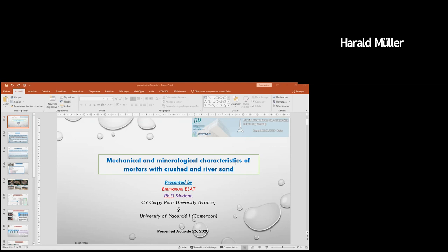And on the other hand, if you look at your slides, on the left-hand side you showed the differences in compressive strength, which has been a little bit questioned by Arnaud. On the right-hand side, you showed the shrinkage behavior, and your explanation for the low strength was the porosity of the river sand. Then the shrinkage should also be quite different, because shrinkage is very sensitive to porosity. This is a decisive parameter for shrinkage. And your shrinkage curves are quite close together. So I think you should check again where these somewhat strange results come from.